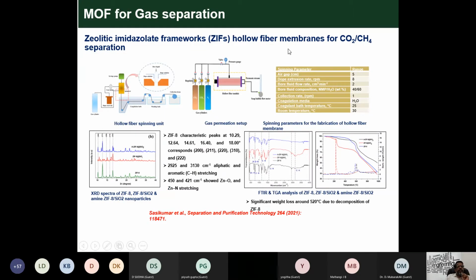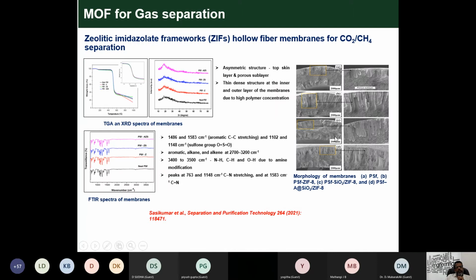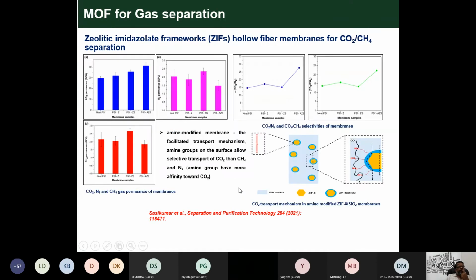Similarly, this is the system we used for hollow fiber membranes, the hollow fiber spinning unit, with collaboration. We reported the properties of MOF and polymer membranes. I told you there is a skin layer followed by a porous layer. The porous layer is responsible for good flux and the skin layer for rejection. Here is how they are occupied on the membrane surface: the yellow color is the polymer matrix, and the dark blue creates interconnectivity between the polymer and inorganic phase due to the gap. So there is transport of molecules.